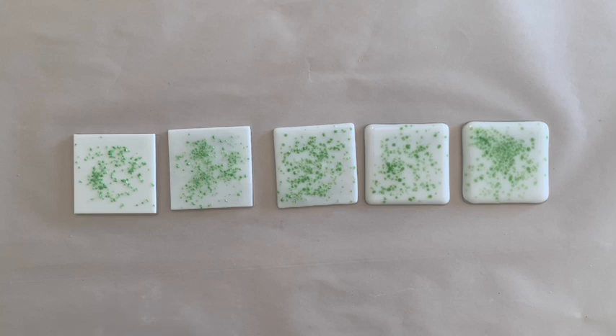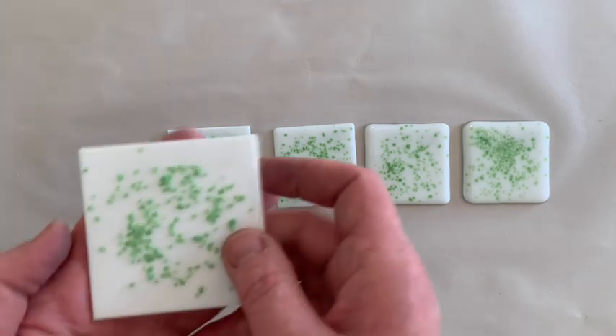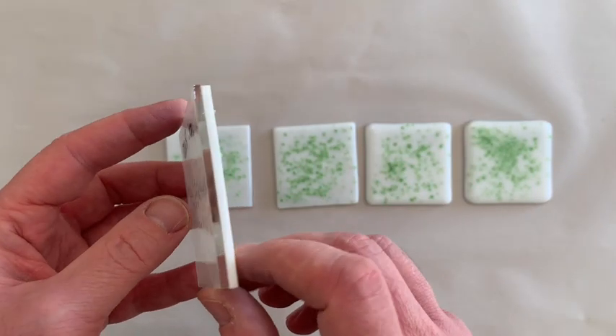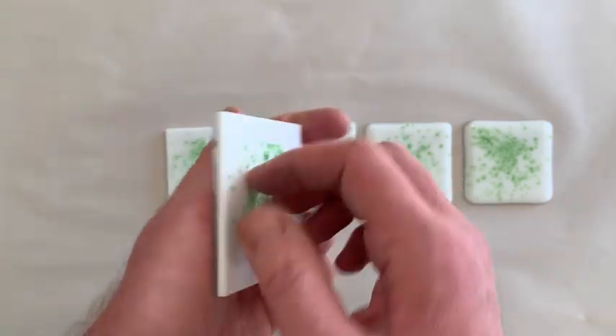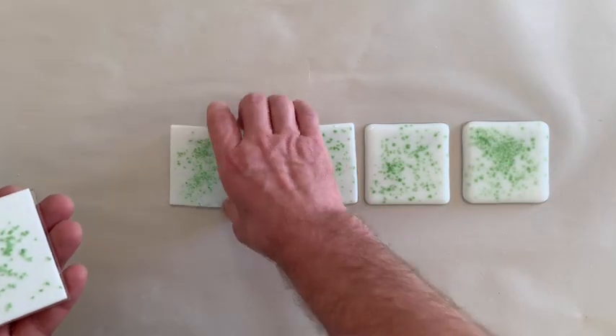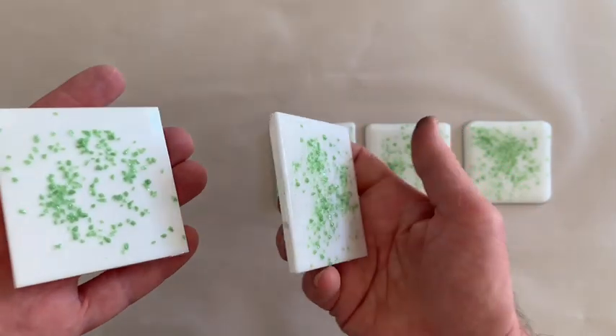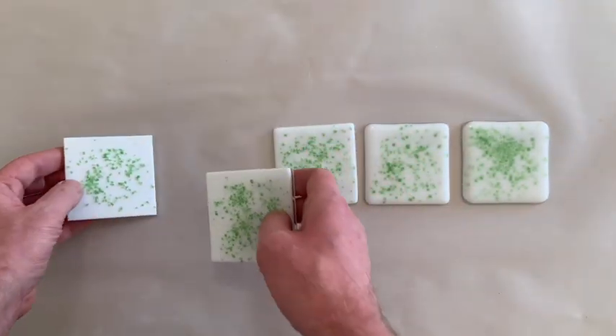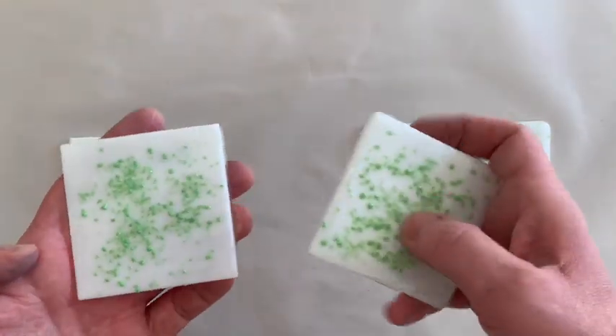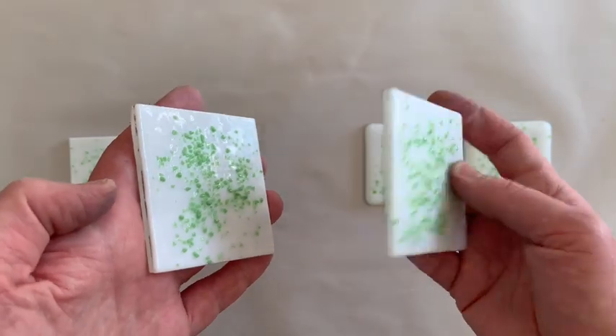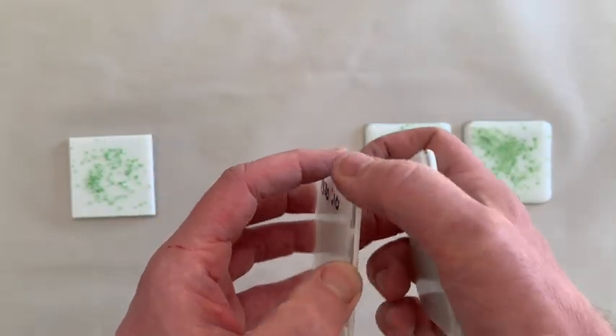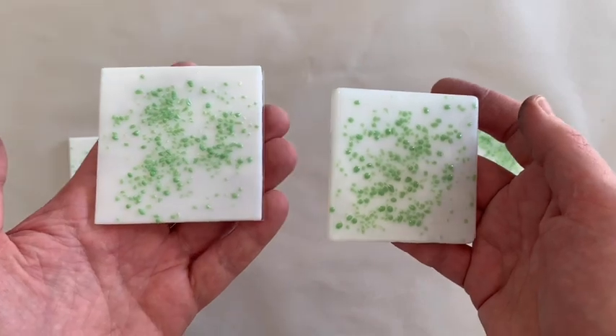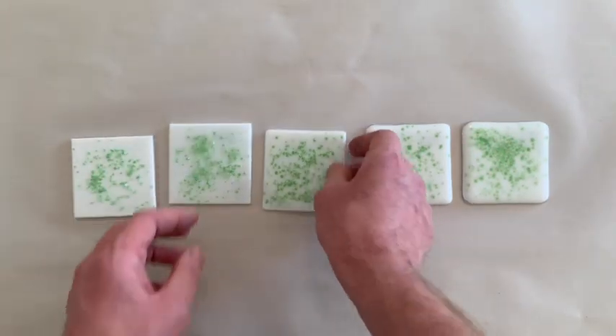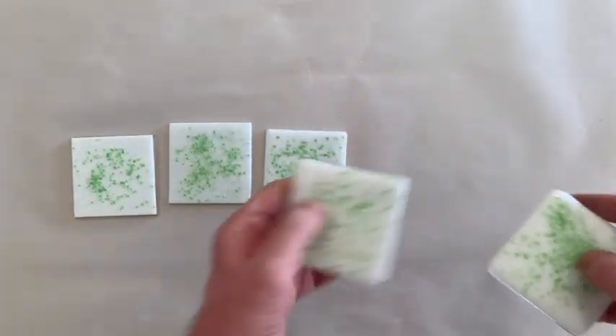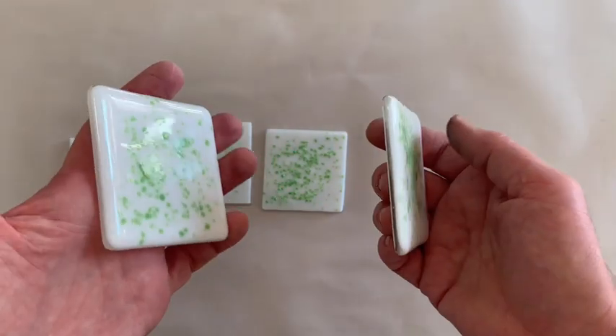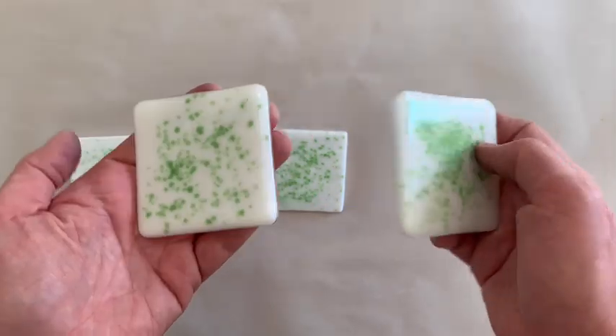The medium olive green frit does tack at 1265 degrees, but is very grainy. At 1320 degrees Fahrenheit, the medium frit begins to soften quite a bit. Notice how the sample fired at 1375 degrees has much softer edges than the 1320 degrees. The sample at 1420 degrees is fully fused into the base piece, as is the 1460 degrees Fahrenheit sample.